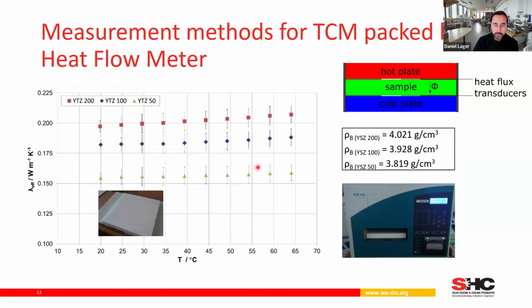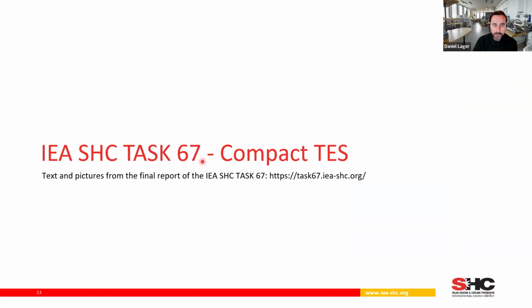Here's another example where we measured the same material with a so-called heat flow meter, which is also a possibility to measure the thermal conductivity through the packed bed. And you see here the dependence of the thermal conductivity on the packed bed density, or bulk density, you have. So the packed bed density strongly influences the effective thermal conductivity of your measurement. So that was more or less to show you the challenges in the measurement.